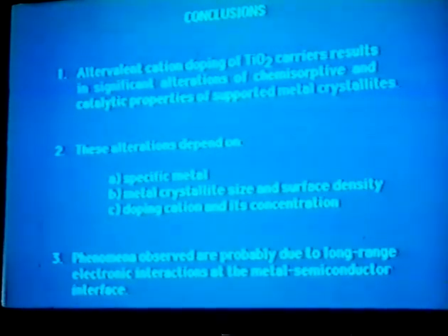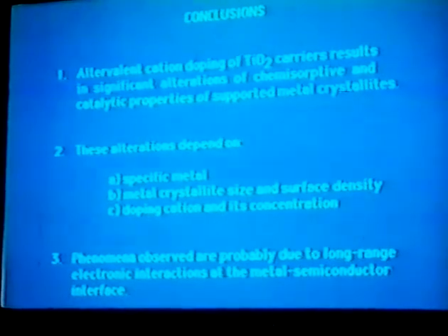It seems that altervalent cation doping of titania carriers results in significant alterations of both the chemisorptive and the catalytic properties of the supported metal crystallites. These alterations seem to depend on the specific metal, on the metal crystallite size and surface density, which I have not shown, and on the doping cation and its concentration in the carrier. The phenomena observed are probably due to long-range electronic interactions at the metal-semiconductor interface, and I should probably add that these interactions, which are induced by doping of the carrier, could be used to alter the activity and the selectivity of metallic surfaces in a desired direction. Thank you.